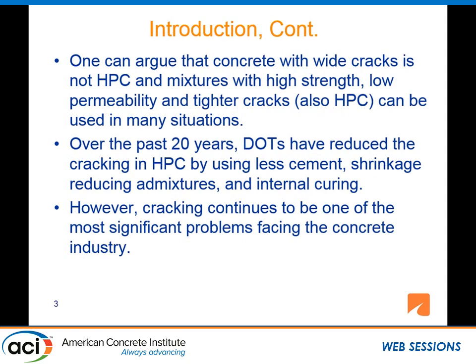Now, one can argue, in fact, when I wrote the paper around which this presentation was prepared, one of the reviewers said, well, if it's got cracks, it's not high-performance concrete. And so one can argue that concrete with wide cracks is not high-performance concrete, and that mixtures with high strength, low permeability, and tighter cracks, which would really be high-performance concrete, can be used in many situations. Over the past 20 years, DOTs have reduced cracking in high-performance concrete by using less cement, shrinkage-reducing admixtures, and using lightweight aggregate for internal curing.